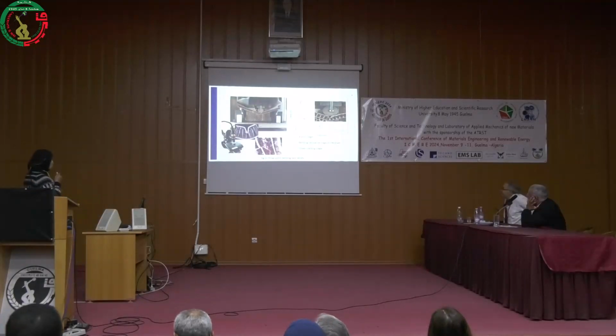So figure 3 shows the failure mode of the honeycomb structures, and the next figure explains the load as a function of the deflection. We can distinguish 3 different stages: an elastic stage with a peak, a maximum value, a bending resistance stage with a rough drop of the maximum value, then a stacking stage that goes with a decrease of the load down to a maximal deflection.